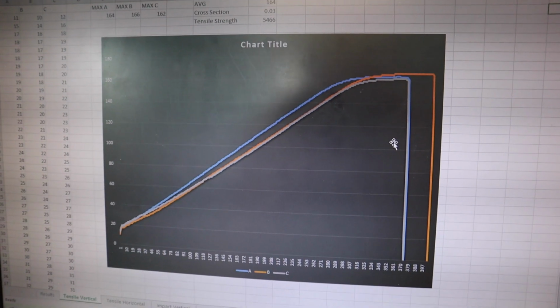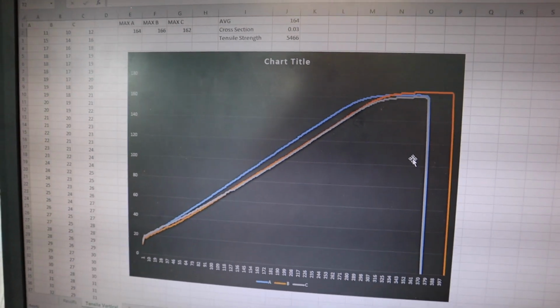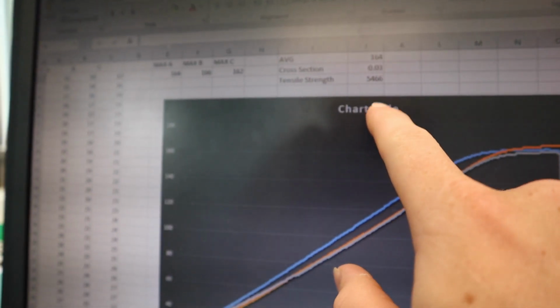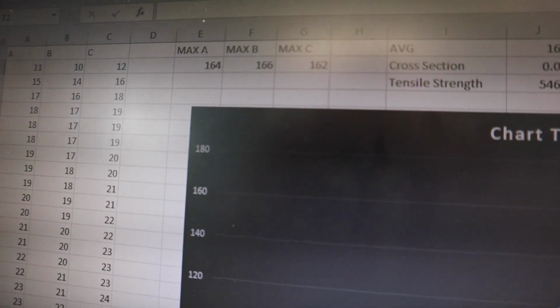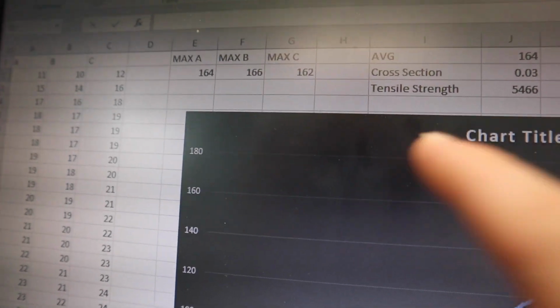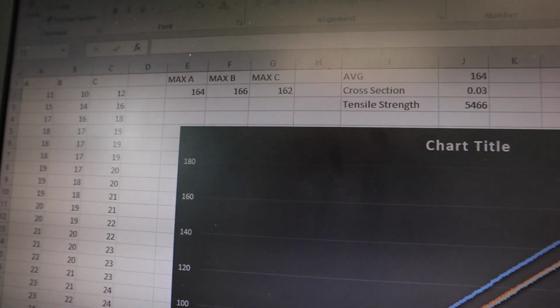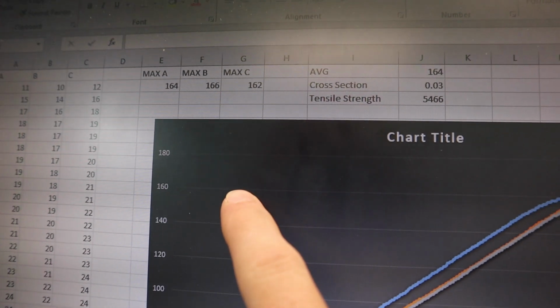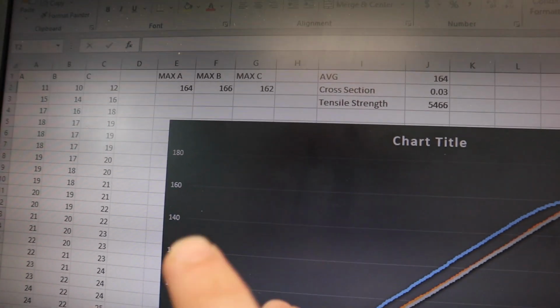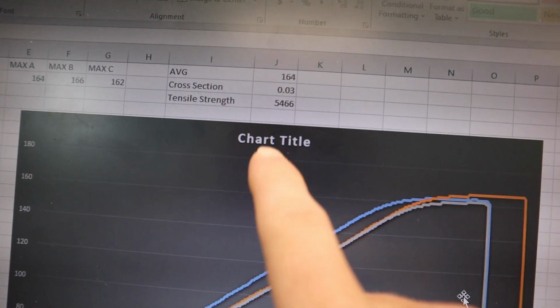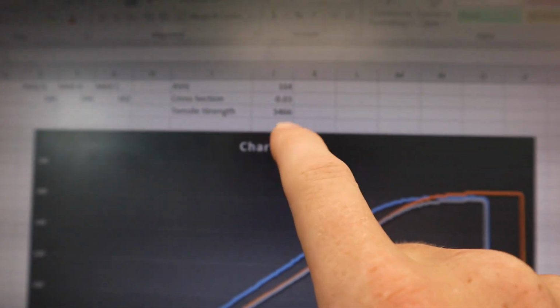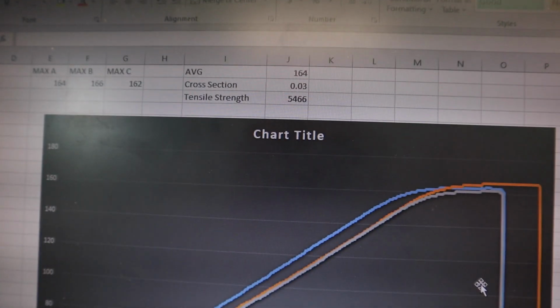Okay, so here are the results of the vertical tensile tests, and as you can see, we came in at like 5,500 PSI, and we were pretty consistent. That is actually very consistent, so pretty pleased with the consistency, especially for vertical tests. Layer adhesion tends to not be as consistent as horizontal tests. So the tensile strength is 5,500, which is really good for a vertical tensile test, so that's pretty good layer adhesion.